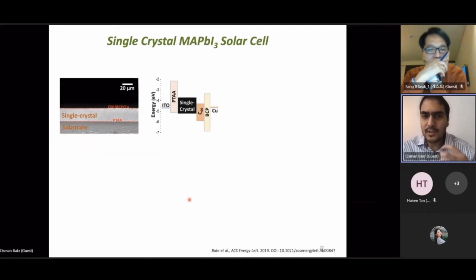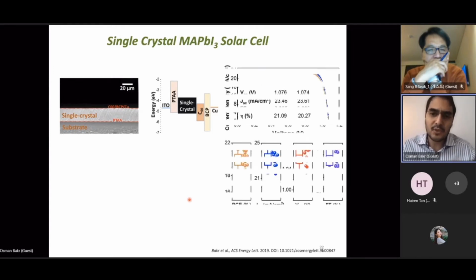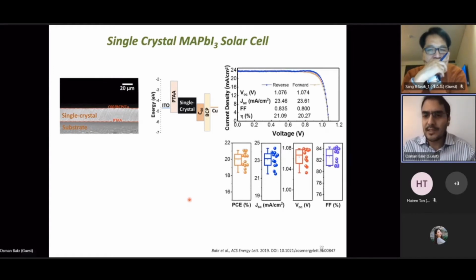And so what we noticed is, if we grew the crystals under more controlled conditions, if we were very careful about the interface and how we use fresh solutions and everything, we realized that actually we could grow single crystal solar cells that are 20 microns thick, but have efficiencies that are more than 21%.